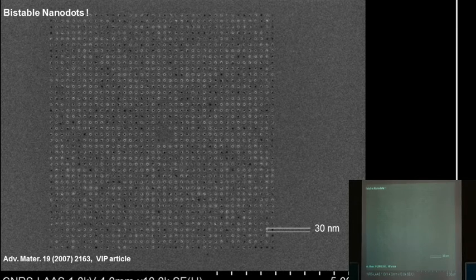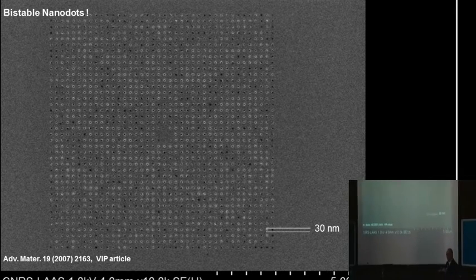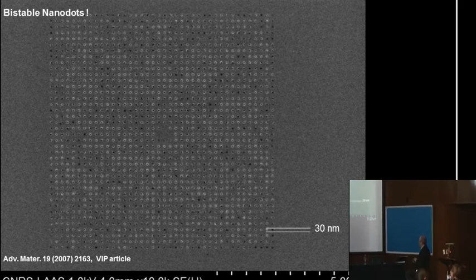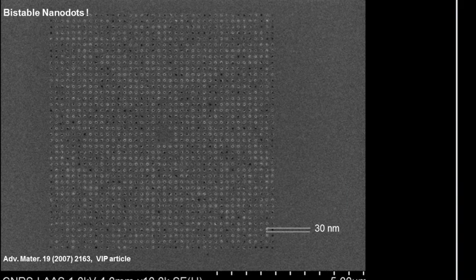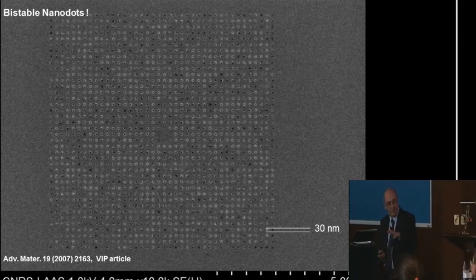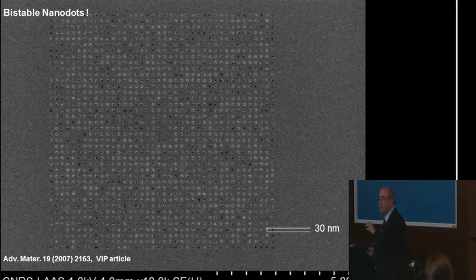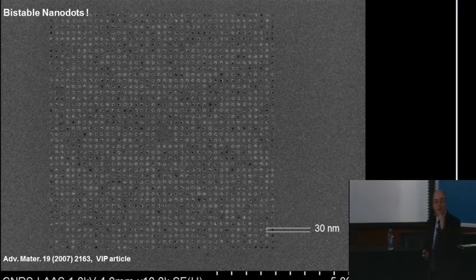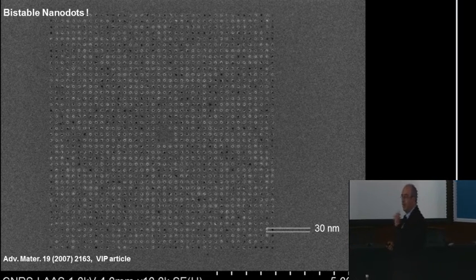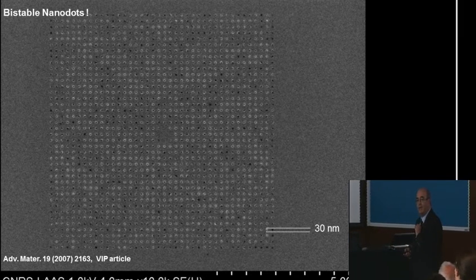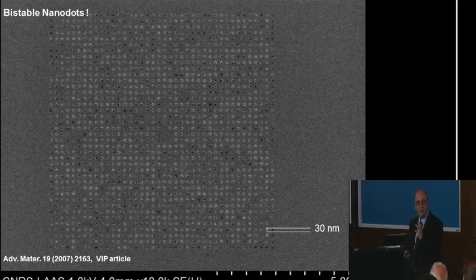Because the question is, do we still have our hysteresis loop at 30 nanometers, okay? So then, of course, we have this very well organized surface, and then we have 30 nanometers here. The spin crossover here of the dots is between the low spin state, spin 0, diamagnetic, and the high spin state, spin 2, paramagnetic. Today there is no machine that can measure the magnetic properties of one dot. It's very complicated because you have a very low change of magnetization at 30 nanometers. So then we wanted to see if we can find something in chemistry in order to measure if we have or not this hysteresis loop.